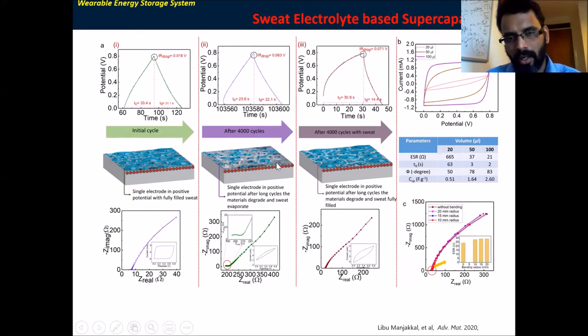So I was thinking, what actually happened? Is there any problem in the electrolyte or the electrode? Then I did an SEM analysis also. I noted that the surface of the material, due to the redox reaction, had some disintegration and some chemical reaction occurred. Then I dropped the electrolyte again and checked the performance. It showed performance, but not as much as the initial cycle. That means the material stability on top of the cloth has a strong influence.